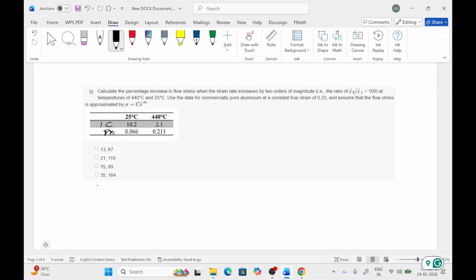So if we calculate it, first for 25 degrees Celsius, sigma 2 by sigma 1 will be, C will cancel out, so we can write epsilon dot 2 by epsilon dot 1 raised to power m. So it is 100 raised to power this m value 0.066. So this will be equal to 1.35.